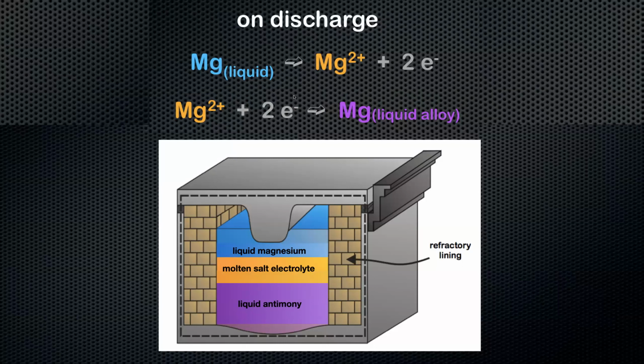And to become magnesium ion, this thing loses 2 electrons, and the 2 electrons go through the external circuit, and they return to the antimony, where magnesium becomes a neutral, and now you make alloy on the bottom. So over time, the top layer grows thinner, and the bottom layer grows deeper. And that's how the cell discharges.